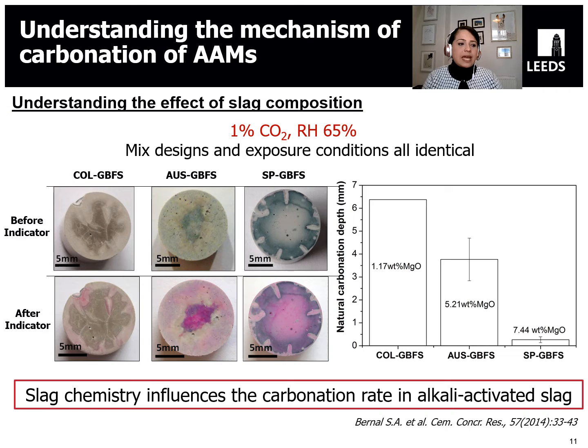So this, I will say, was a milestone scientific point in my career, because when we did this study, we managed to identify that one of the key differences in the three slags that I was studying at the time was the magnesium content. So the Spanish slag was very standard for European slag. The Australian one is fairly standard for Asia. The Colombian one is a quite unique type of slag that unfortunately is no longer produced with this sort of composition.